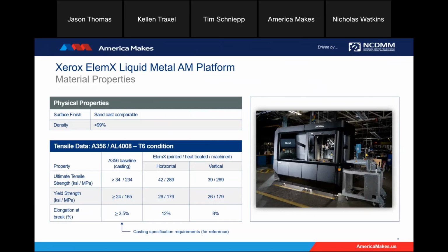But some degree of anisotropy shows up, and we attribute that to some natural greater variability in the Z direction, both in the surface profiles, as well as a thin oxide layer that builds up during printing, even though we flood the head with argon gas that provides a shroud and follows the droplets all the way down to the build plate. You still do get some oxide buildup. It's very thin. Some materials like the 4008 series alloy that we offer now are pretty tolerant of that. Others can be more sensitive.